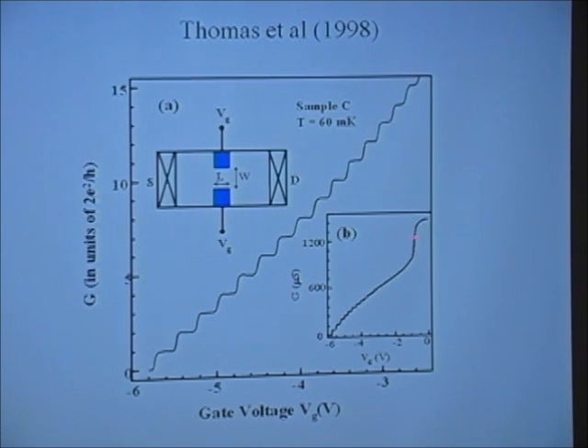This is the 2D electron gas. Now the 1D region becomes high resistance and takes over, and we blow up these steps here, and that's what you see. This is a very low temperature experiment, 60 millikelvin. And that's what one sees in experiment. The jumps are 2e squared upon h. It is possible to actually apply a magnetic field and make it e squared upon h, but that doesn't change the principle of the thing.